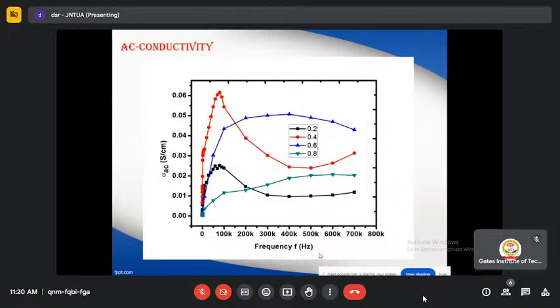The frequency dependence of AC electrical conductivity is shown in the figure. The graphs for frequency versus AC conductivity at different compositions of 0.2 to 0.8 are shown here. This has been done up to a frequency of 700 kilohertz. After 70 kilohertz, the x equal to 0.2 and x equal to 0.4 samples exhibited small relaxation behavior, and above the relaxation frequency of 70 kilohertz, a swing type trajectory of the graph was obtained. The reason for this is the matching of the jumping frequency of charge carriers. The trapped charge carriers within the dislocation centers, interfaces, and lattice distortions may be accountable for this sort of behavior.